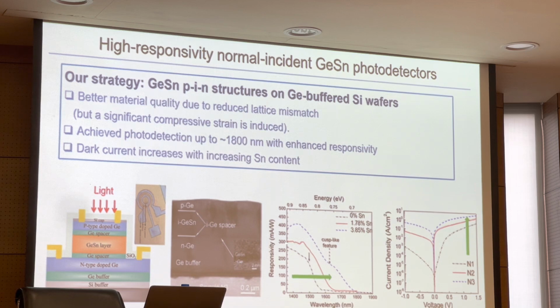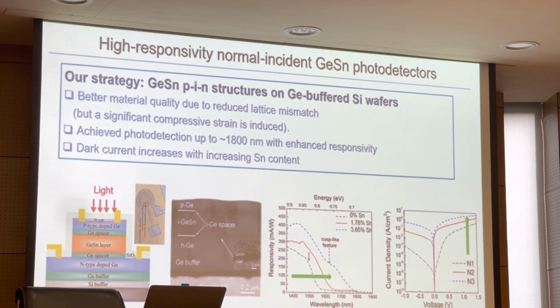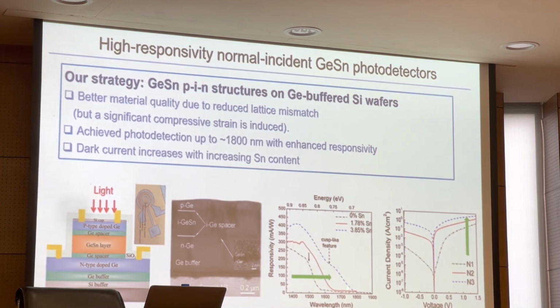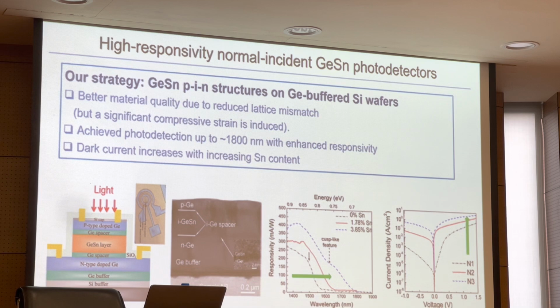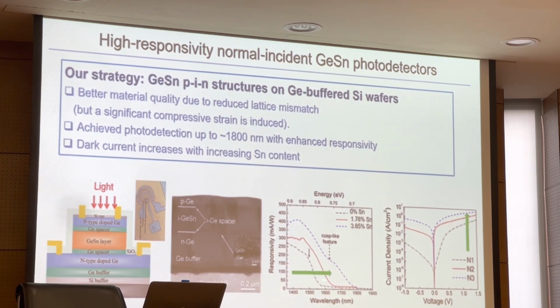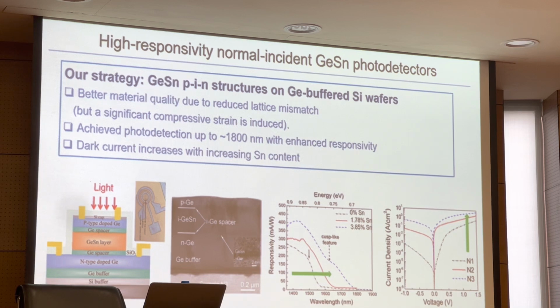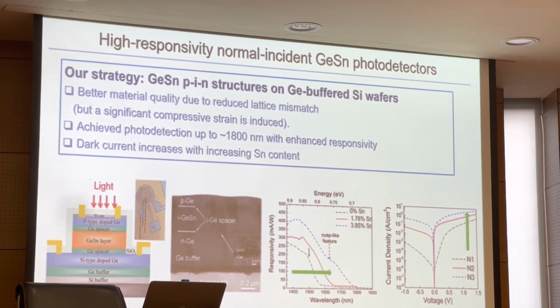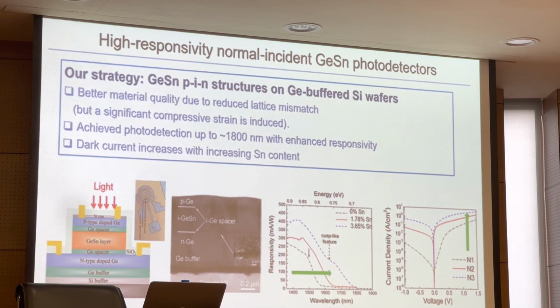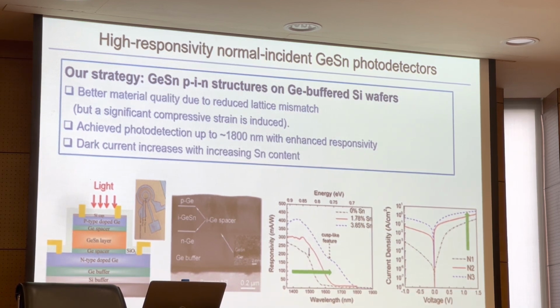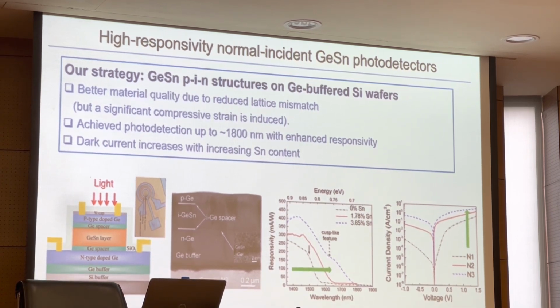With the increase of tin content, we can see the responsivity curve shift to longer wavelengths, so we can extend the photo detection range of the photodetector. For the sample with 3.85% tin, the cutoff wavelength has been extended to 1.8 micrometer. These devices can cover the entire telecommunication band, which is typically from 1.26 micron to 1.67 micron, so our devices are very useful for fiber optic telecommunications.